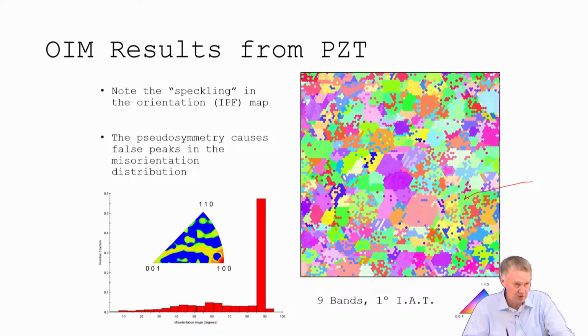Basically, you'll have 0 confidence if you put both those different phases in, because it will say, you know, you have 30 votes for A and you have 30 votes for C. So that means the top 2 solutions are the same, so you have 0 confidence because you subtract those from each other. So you can't go in and just use confidence index to clean the data.